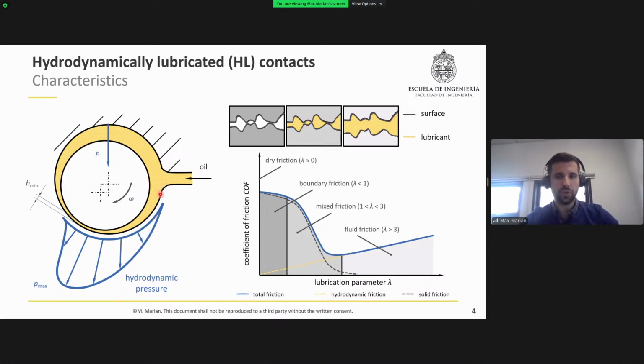And if lubricant is drawn into the contact, as exemplarily shown here for a radial hydrodynamic journal bearing, hydrodynamic pressure can build up, and it can thus lift and separate the surfaces. With sufficiently high velocity and/or viscosity or lower loads, the fluid regime can transition from boundary to mixed, and finally fluid or full film separation, which means first we have a partial separation of the contacting bodies, and with higher velocity or viscosity or lower load, we might have a full separation of the contacting bodies. And the coefficient of friction typically follows the well-known Stribeck curve that probably all of us are very familiar with.